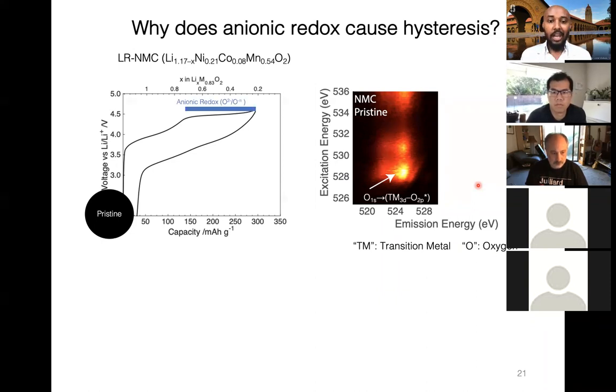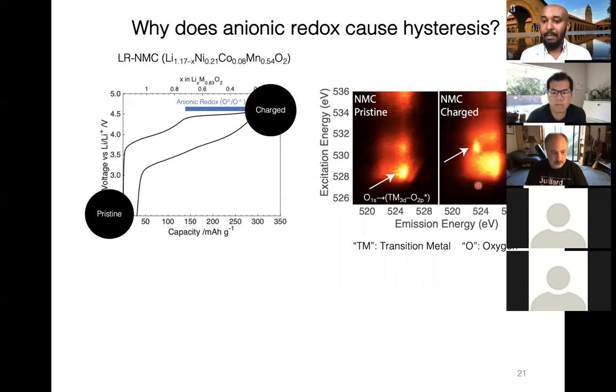So after charging and after anionic redox, here is what the RIXS map looks like. And as you can see, in addition to the bright feature that exists in the pristine state coming from the metal-oxygen hybridization, we have this peculiar feature that's appearing around 531 eV in incoming energy and 523 eV in emission energy. This peculiar energy tells us that upon anionic redox, we are forming a new species in the material that can describe the mechanism of anionic redox.